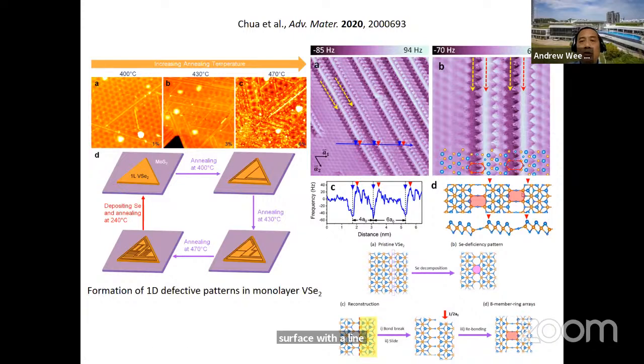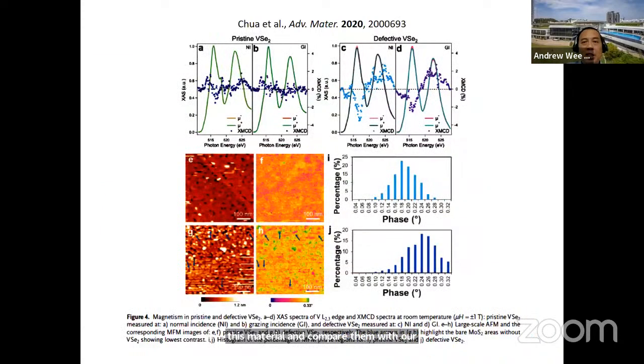So we wanted to do the magnetic measurements of this material and compare them with our control undefective material. So we did XMCD again, and we did MFM as well. XMCD for the clean surface, as expected, is near zero. For the defective surface, you see the XMCD signal is non-zero, right? You see some background here, certainly higher than here.